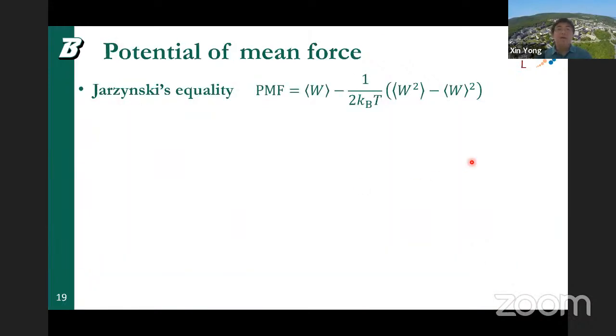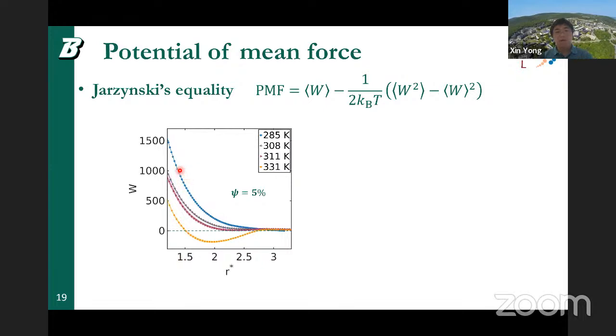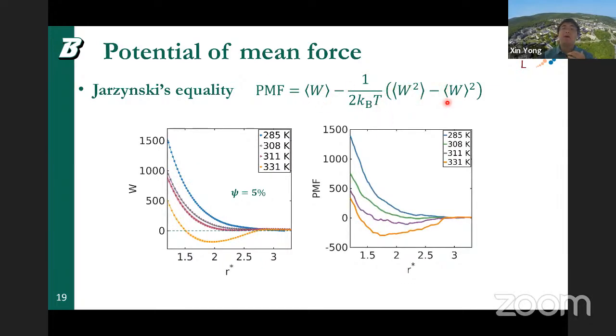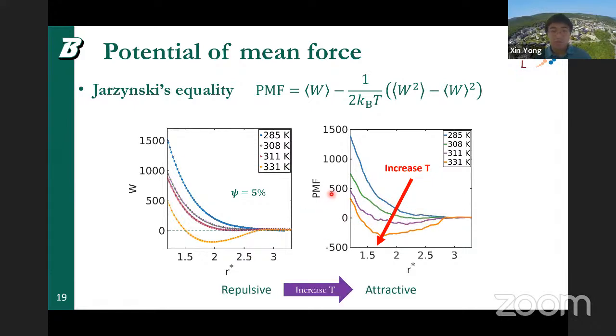And so we could quantify the interaction energy by calculating the potential of mean force from the steered MD, for which we utilize the Jarzynski equality, which calculates the work done by this spring which pulls these two microgels together. This is the original data, which is the work, and then we can obtain the PMF from its statistical variation. And so this is the obtained PMF. What I want to demonstrate is that as temperature increases, the free energy profile of two interacting microgels changes from pure repulsion to attraction, exhibiting an attraction well. So in the region where they overlap, based on their distance, there is an attractive well. That's a very important observation.